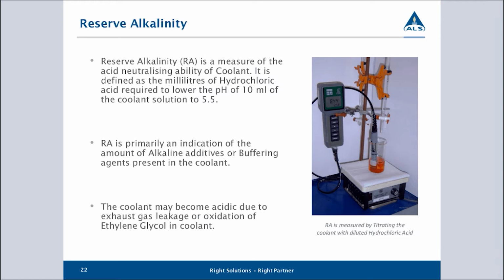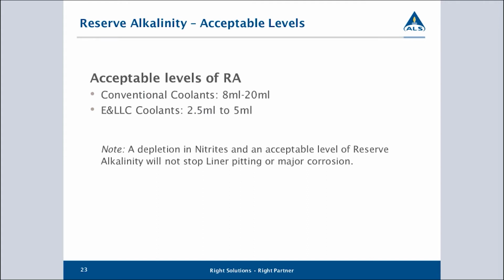So for some coolants, we know that we're going to see thermal degradation of the glycol. We know that acid is going to be formed, so we need to buffer the coolant to absorb that acid to prevent it causing any sort of acid corrosion in the system. The reserve alkalinity is a means of measuring that buffering potential. And how much buffering the coolant can take depends very much on the chemistry that the formulators put into it. So we do see a range of potential values that could be reported.